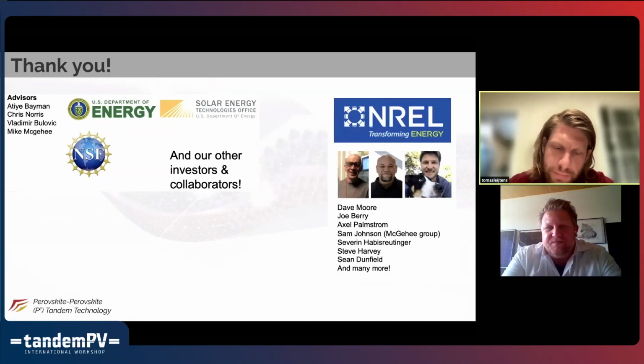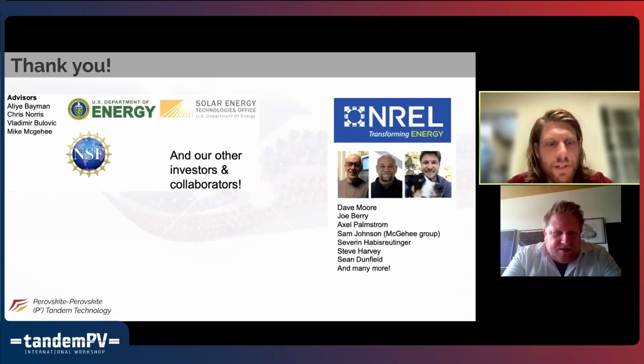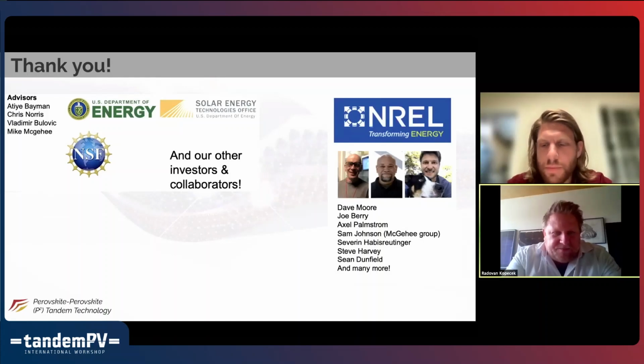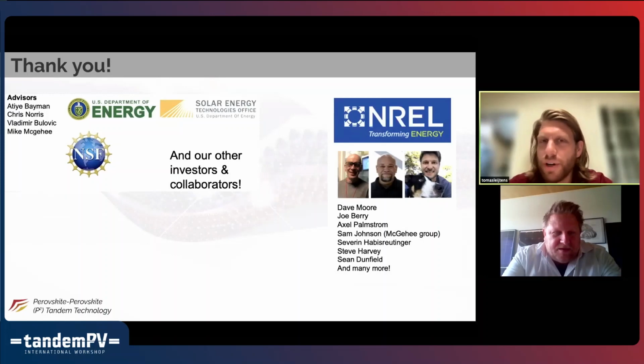Octahedral tilting? Yes. Of the lead halide octahedra, I imagine. Yeah, I suppose many perovskite materials, especially if they're in the tetragonal phase, will have octahedral tilt. It's also an interesting way of tuning the band gap, actually, using octahedral tilting. Oh, I imagine this is referring to maybe the DMA incorporation. Yes, octahedral tilt is a very important parameter for the band gap, because I think as most of you know,